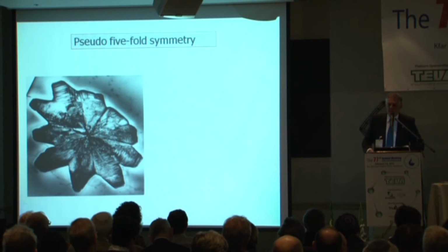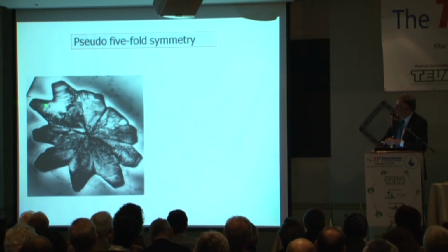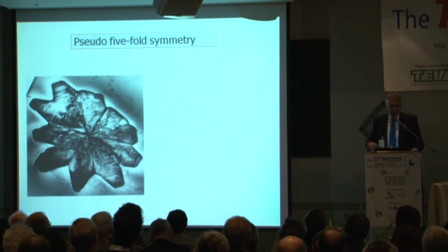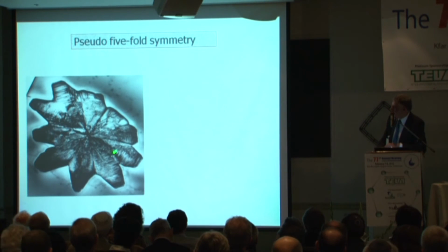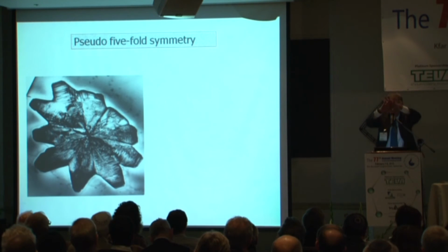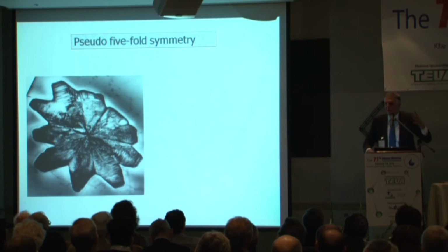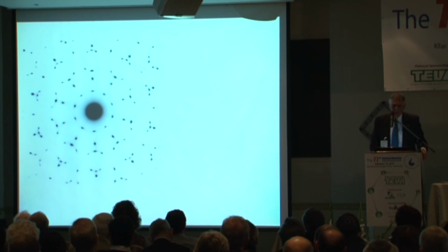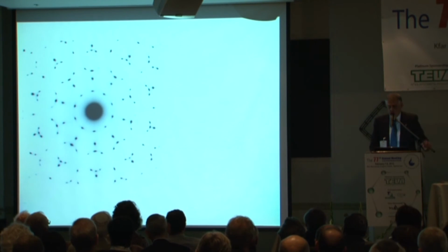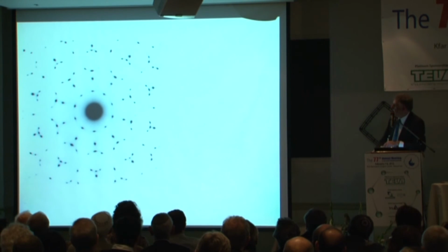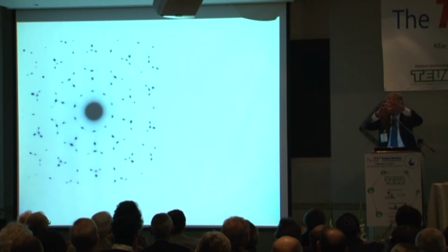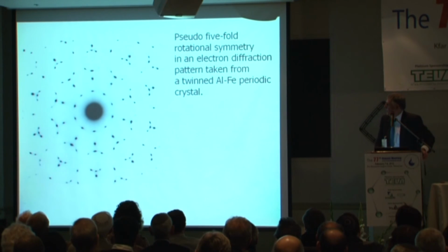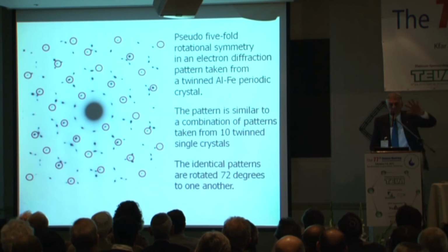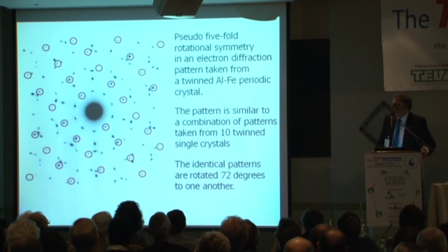Now, you can clearly understand that if you take a diffraction pattern from one single crystal, you have a periodic diffraction pattern. But if you take a diffraction pattern from all of them together, then you have 10 superimposed diffraction patterns, which are periodic, and obviously you will have a 10-fold rotation symmetry. So here is the picture. This is the actual picture I took from that actual crystal. And as you can see here, there is a 10-fold rotation symmetry, obviously. However, we know that it emerges from 10 different crystals, and if you want to see one of them, here's just one of them. If you do that 10 times, then you get the diffraction pattern. So this is pseudo 10-fold diffraction, the pseudo 10-fold rotation symmetry.